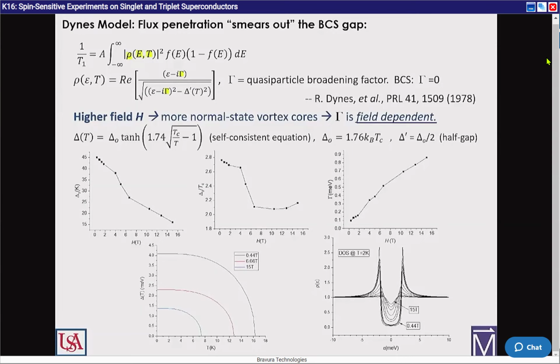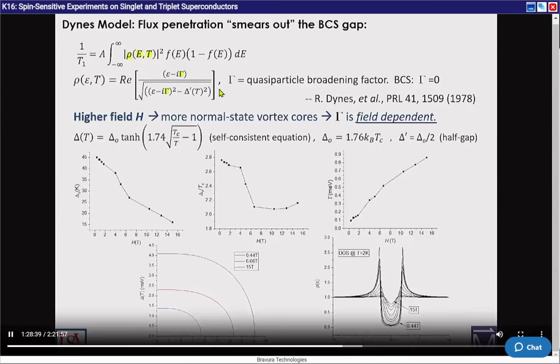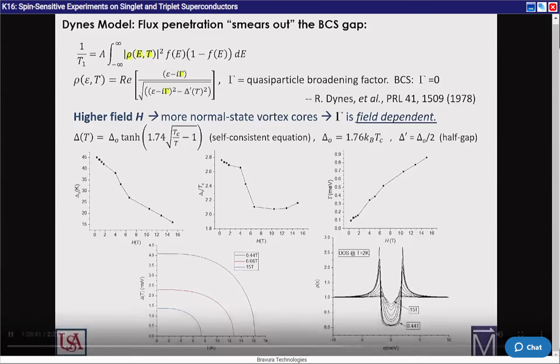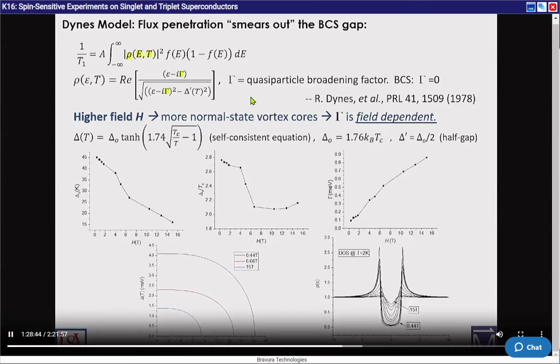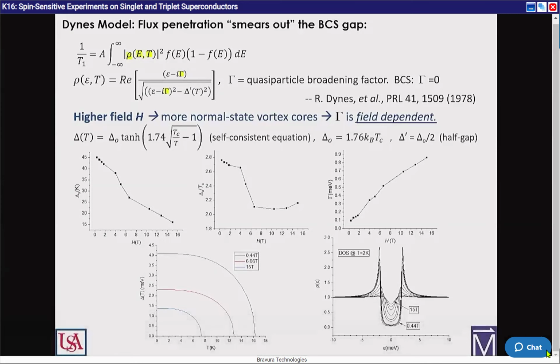Guess what happens? It just pops right out that gamma is monotonic with field, which is consistent with the idea that the lifetime is, in fact, broadening as you increase the field. So we are, in fact, messing with the electronic structure itself, and that smears out your density of states in a pattern that's familiar to people who do tunneling experiments.